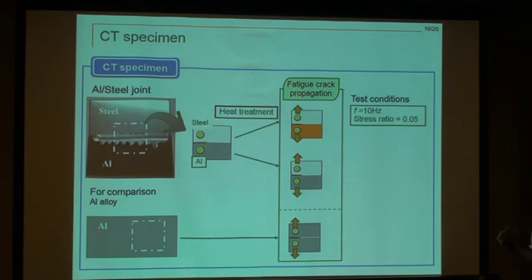As you can easily imagine from the tensile test, the crack might not propagate along the interface, but it might deviate into the aluminum side because the hardness of the aluminum side is decreased. So, to avoid this deviation and to let the crack propagate along the interface, we did the heat treatment again to recover the hardness. So we prepared two different samples for the crack propagation test of the dissimilar welds. And for comparison, we also prepared another sample of the aluminum alloy. And this is the test condition: a frequency of 10 Hz and a stress ratio of 0.05.